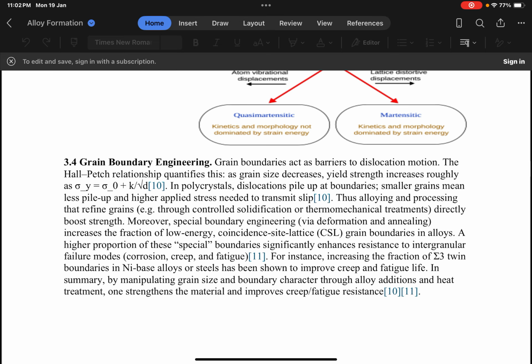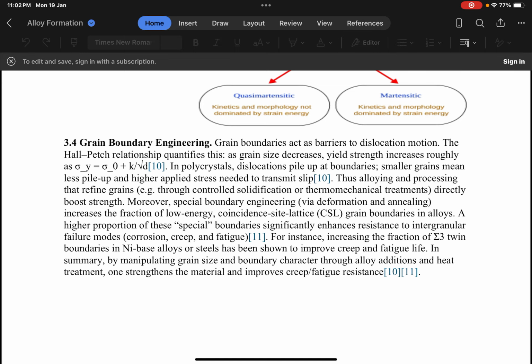Now let's talk about the number 4 mechanism, that is grain boundary engineering. Grain boundaries act as barriers to dislocation motion. The Hall-Petch relationship quantifies this: as grain size decreases, yield strength increases roughly. As you can see in this equation, in polycrystals, dislocations pile up at boundaries. Smaller grains mean less pile up and higher applied stress needed to transmit slip, thus alloying and processing that refine grains through controlled solidification or thermomechanical treatments directly boosts strength.